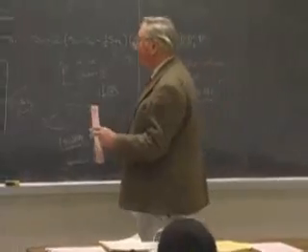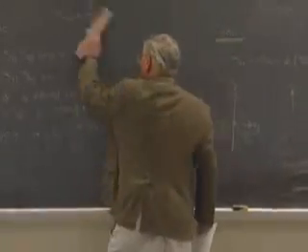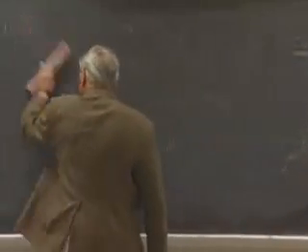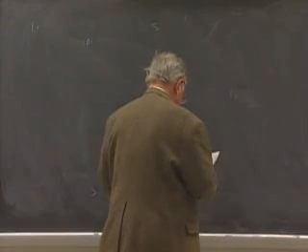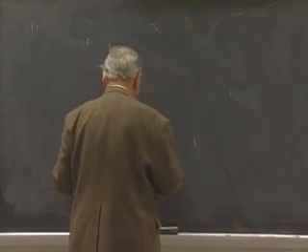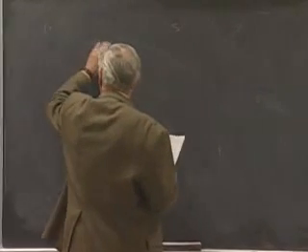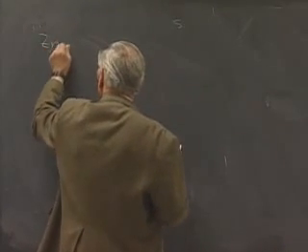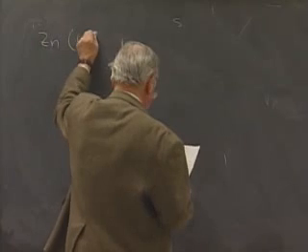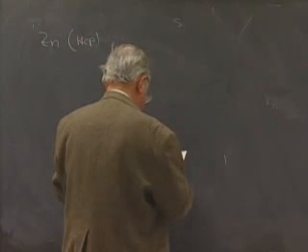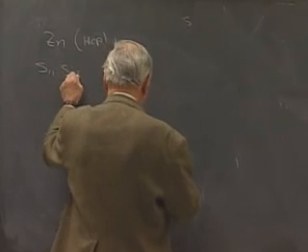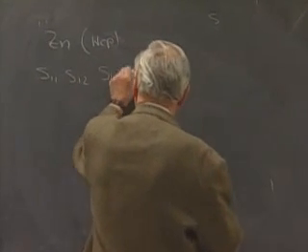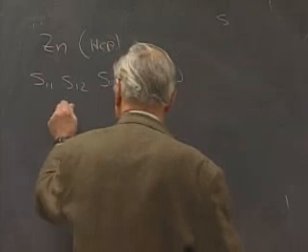Okay, let me give you one other variation that comes straight out of Nye. And this is for a hexagonal crystal that might be a hexagonal close-packed crystal. For zinc specifically, which is a hexagonal close-packed metal, the form of the matrix is S11, S12, S13, 0, 0, 0.